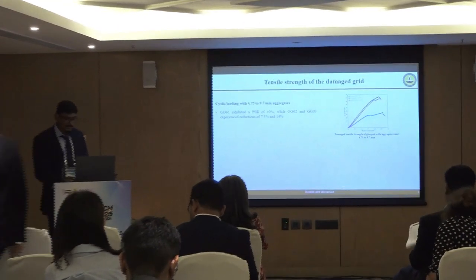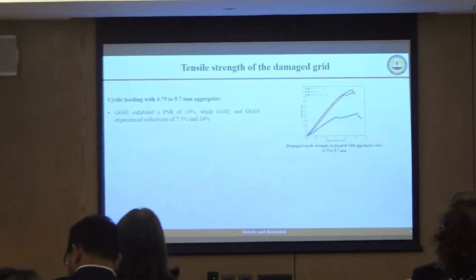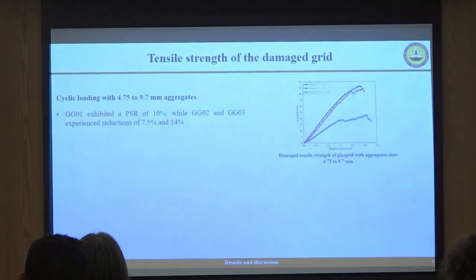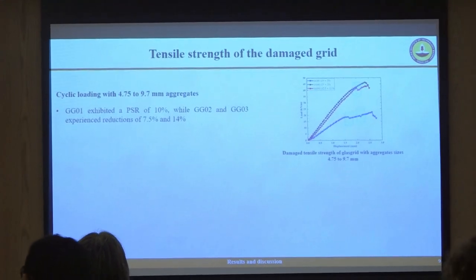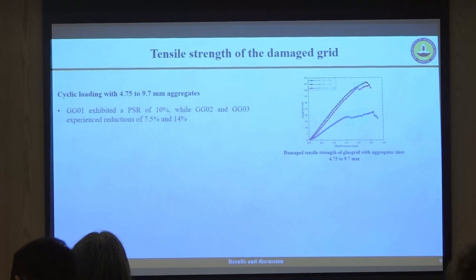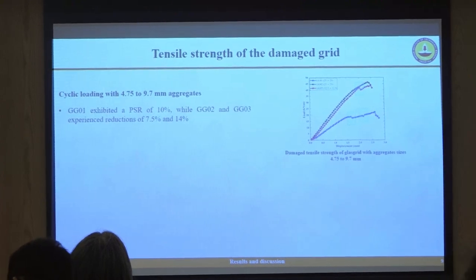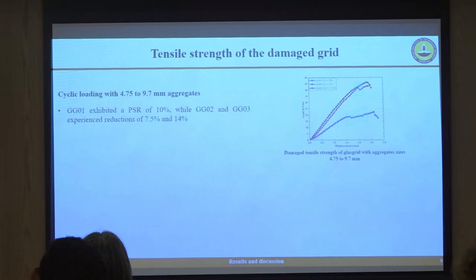It signifies that once the cyclic loading is completed with different ranges of aggregate, we have quantified its tensile strength. As I have already said, we are using three different ranges of aggregate for three different grids. In the first set of experiments, we use smaller aggregate, with a size of 4.75 to 9.7 mm. We noticed that for the GG1 grid, the percentage strength reduction was 10%, while for the GG2 and GG3 grids, the strength reduction was 7.5 and 14%.